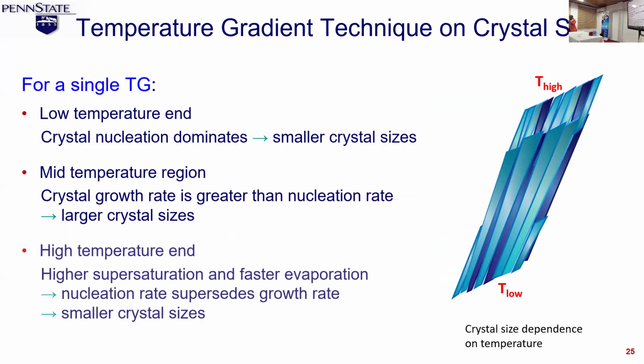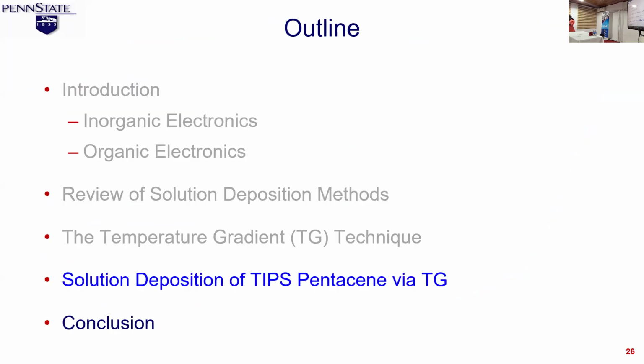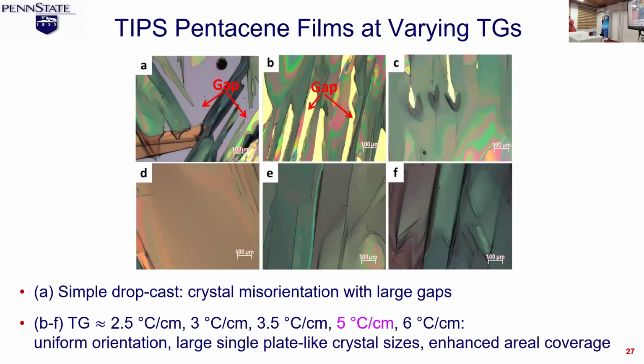And then towards the higher temperature end, the opposite occurs again, where the nucleation rate now starts to supersede the growth rate. The reason is that on the high temperature end, evaporation is higher, because you have high temperature there. So the solvent evaporates a lot more, and nucleation tends to happen faster over there. So the crystal size starts to decrease again. All right. In using the temperature gradient method, there are 5 different temperature gradients that I tested. Image A is just drop casting. These are optical microscope images.